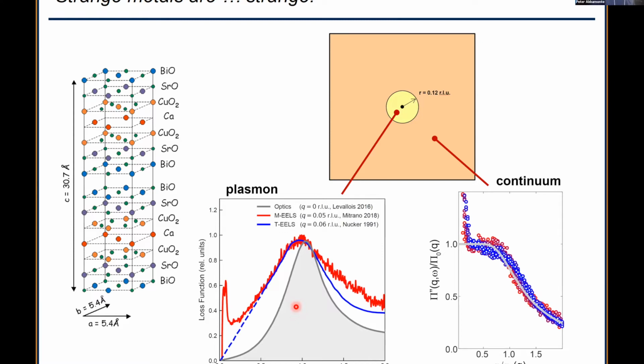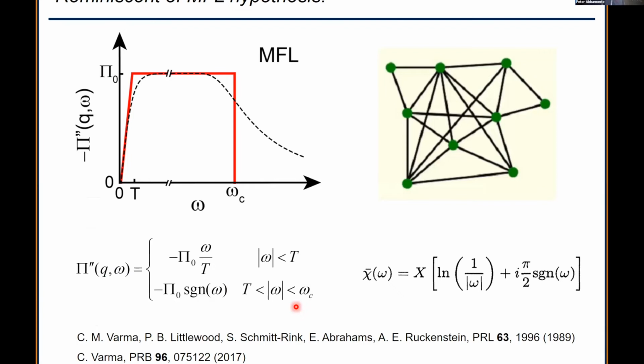It's also constant in momentum, modulo a q squared factor that's needed to satisfy the F sum rule. And the interesting thing about the continuum is it looks a lot like these old conjectures about the marginal Fermi liquid from the late 1980s, early 1990s, in the sense that there is a large region where the susceptibility is constant and it's basically momentum independent. So we've already heard today discussion related to what could be the microscopic origin of this, one being the SYK model, which gives you a frequency independent susceptibility in the imaginary part. So that's just a little bit of background.